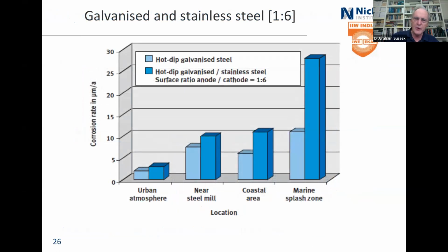This is perhaps a more interesting thing, looking at straight galvanic corrosion. We're looking at hot dip galvanized steel sitting there, there, and there, the light blues, and the hot dip galvanized connected to a bit of stainless steel. It's 6 times the area of stainless steel to the galvanized, so it's a bad ratio. And then we're looking at corrosion rates in micrometers per annum.